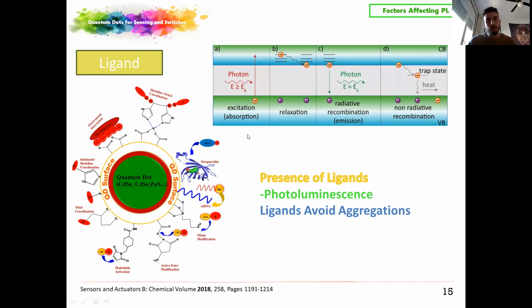In a normal situation, we will have an excitation of the electron by a photon, and after relaxation, this quantum dot emits another photon with a lower energy. However, when we have ligands, they trap these electrons, avoiding the radiative recombination, resulting in a quenching of the fluorescence.